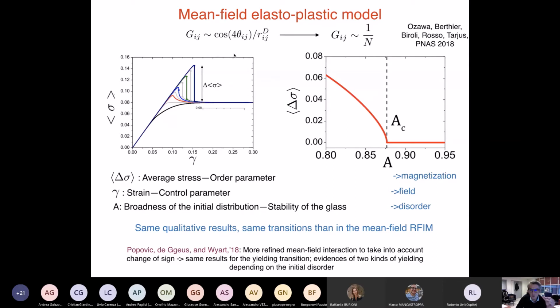And we can compute the stress versus strain curve, changing the initial disorder of the system. I remind you that the disorder is the initial distribution of the sigma, whether they are all similar or whether they have a lot of fluctuation. And again, this is related to the degree of annealing of the amorphous material. What we see in the stress versus strain curve, sigma versus gamma, is a behavior with a discontinuous jump in which sigma increases, then has a jump, and then goes to a kind of plastic behavior. This is what happens when the degree of disorder is small.